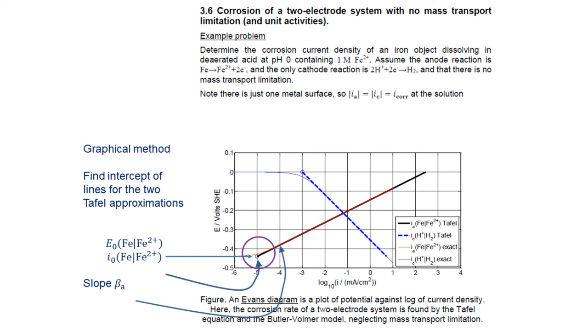That's where the anode current density is equal to the cathode current density. At what single surface potential is that condition satisfied? So I have to draw on my two lines. I draw the black line by putting a point at the start for the exchange current density, 10 to the minus 5 milliamps per centimeter squared for iron, and I do that at the equilibrium potential for the iron, so minus 0.44 volts SHE. That's the thick black line. I draw in the thick black line using its Tafel slope.